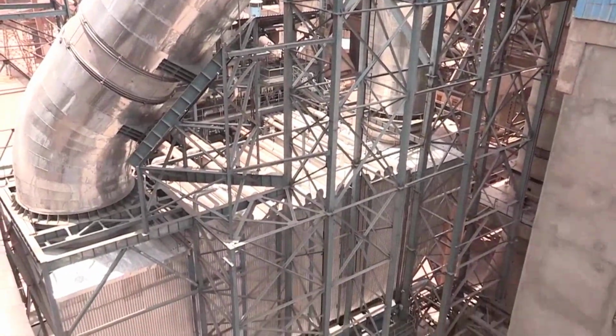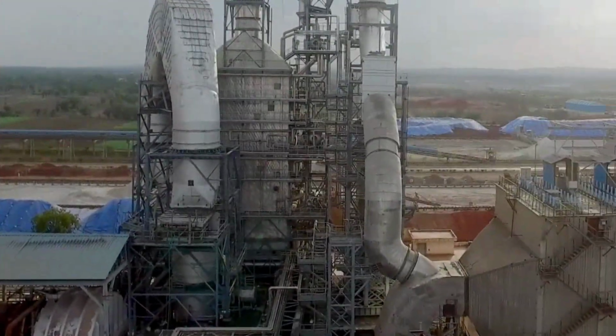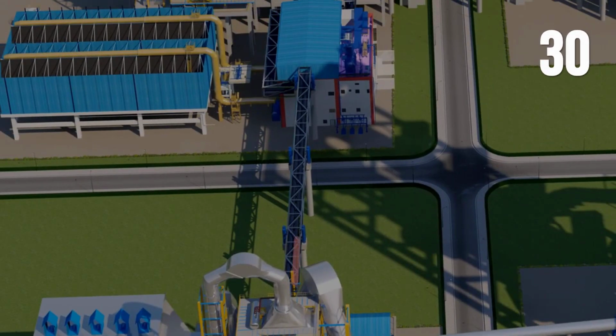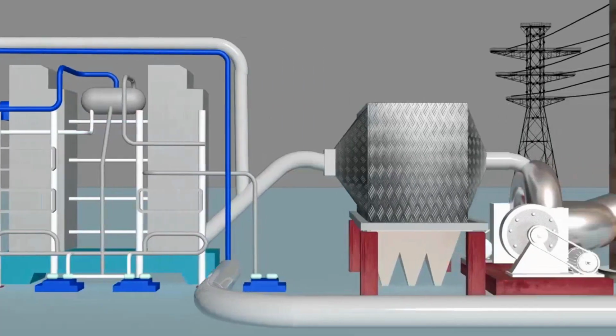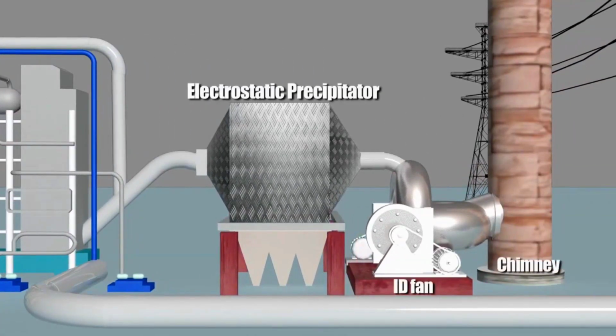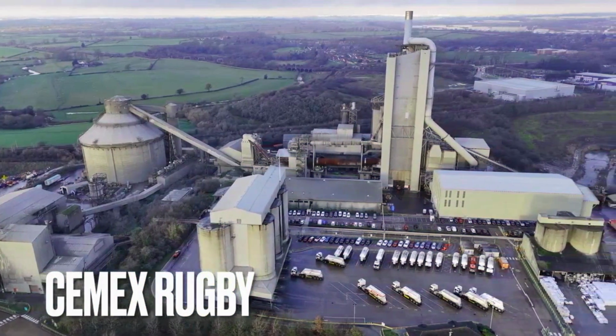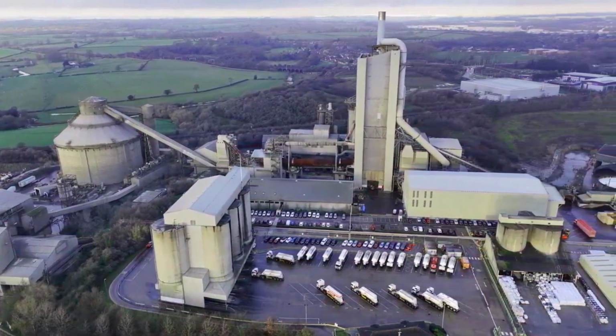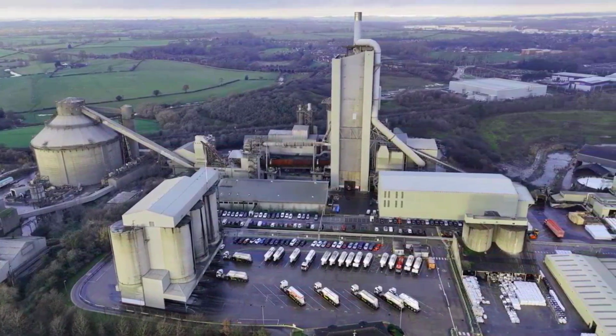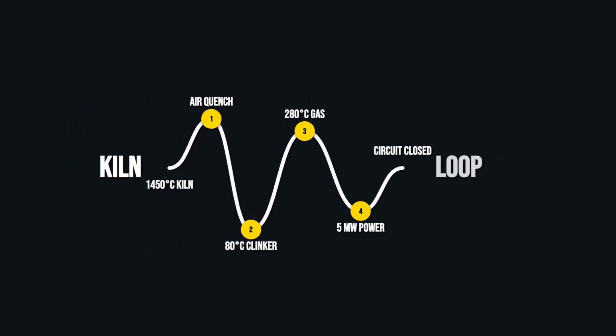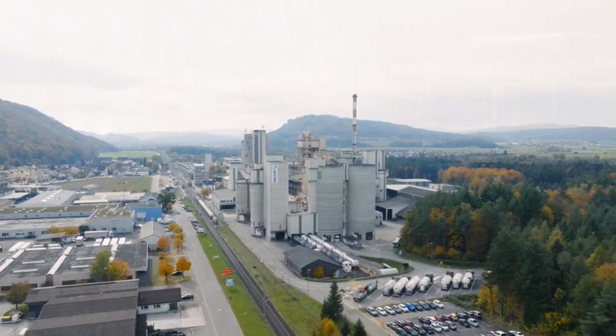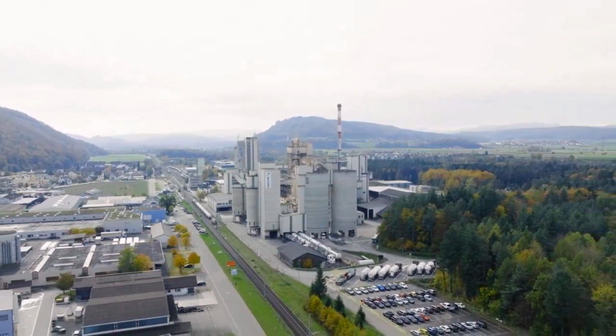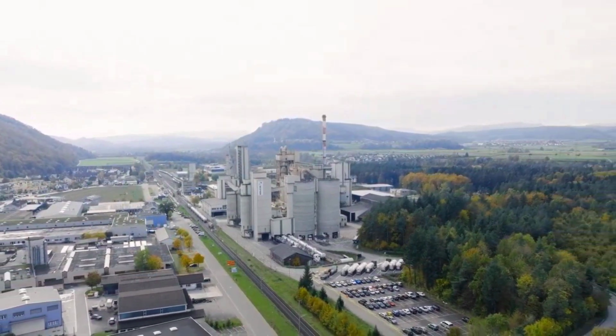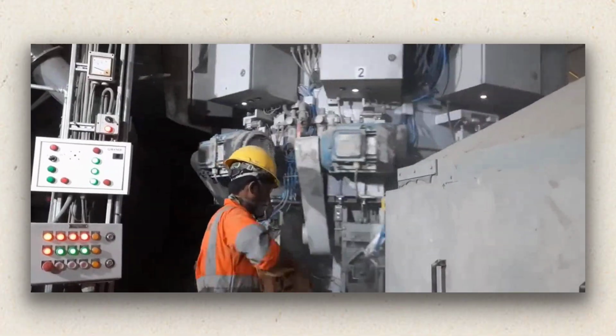Here, waste heat and energy are captured, typically yielding 25 to 30 kilowatt hours per ton of clinker, and redirected to preheat incoming air or generate electricity for the plant. This loop not only improves fuel efficiency, but also stabilizes the power supply, closing the energy circuit that began in the kiln. The result is a process where thermal management, mineral formation, and energy recovery are inseparable, each reinforcing the plant's ability to fill thousands of bags every hour without interruption.